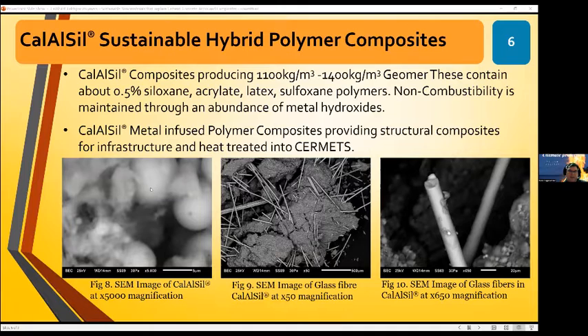So very high magnification here. Just indicates the blurriness. You're talking about 5 microns. These are typically silica fume particles, and even at the scanning electron microscope vacuum, they still retain some water, so the blurriness comes out in the image. This is just an indication of the glass fiber, how the glass fiber looks under the microscope in comparison to the CalAlSil agglomerate at the macro and micro scale. And it's very clear that the glass fiber is much more of a chemically bound material, solid material, not too many breaks in continuity there. So I just might make the point at this juncture to say that these images are from non-combustible CalAlSil resins, meaning I have not put any organic hybridization in them whatsoever. Obviously, with the hybridization, you get a lot better bonding.